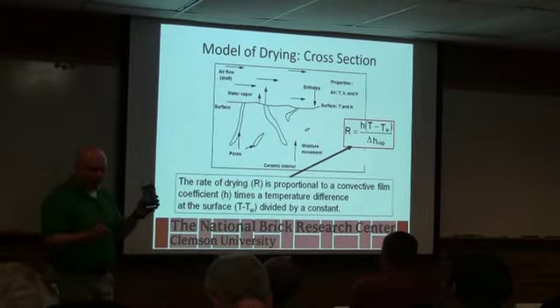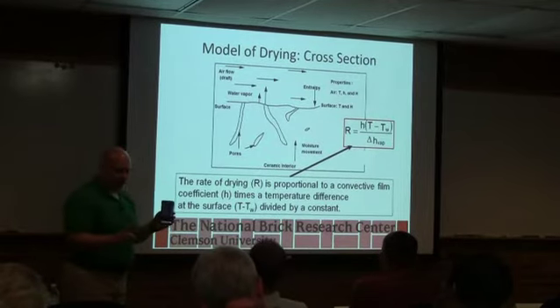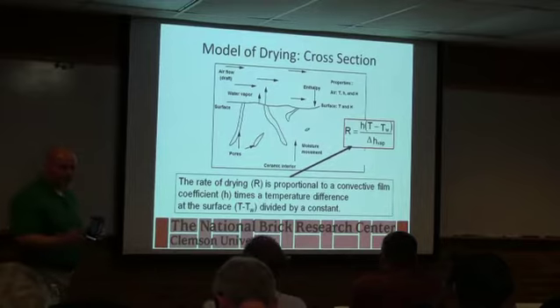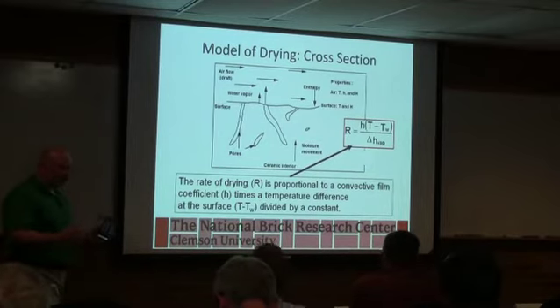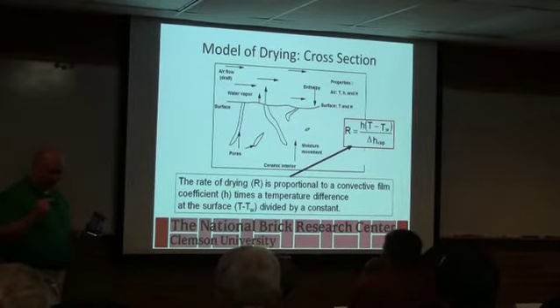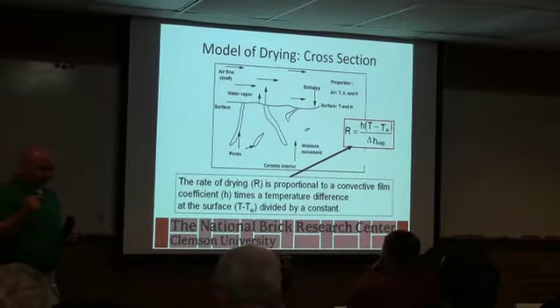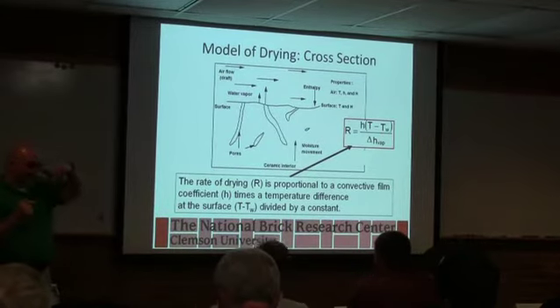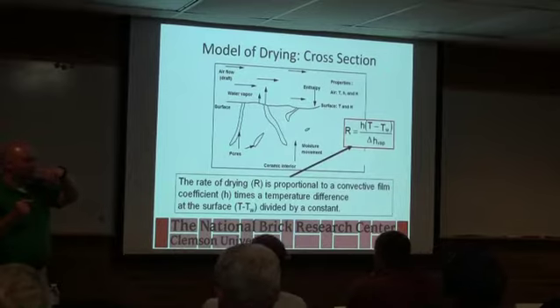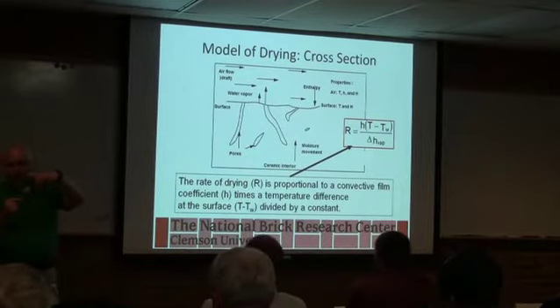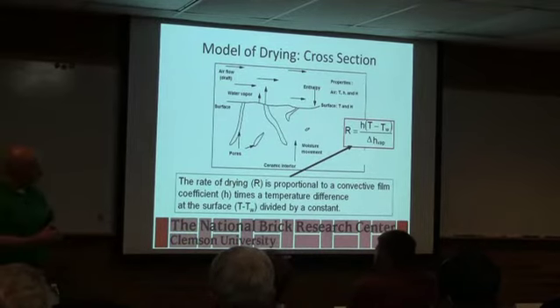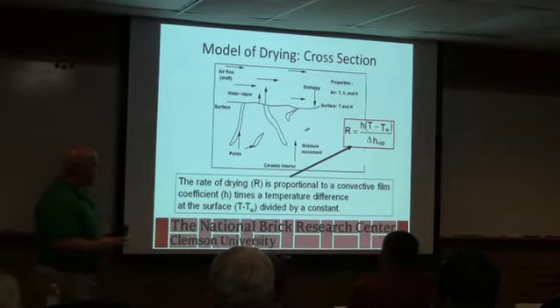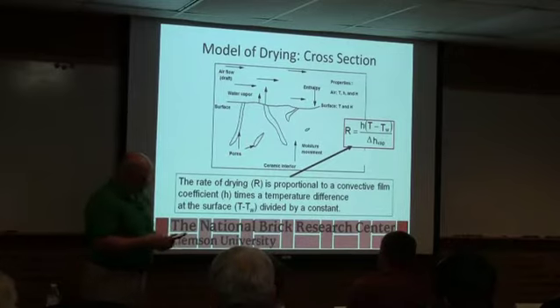Remember, relative humidity is relative to temperature. Okay, so if I'm looking at 50% relative humidity and it's 30 degrees outside, that's one moisture content. If I'm looking at 50% relative humidity and it's 80 degrees outside, that's another moisture content. Big difference in how much actual water's in the air, even though it says relative humidity. So typically when you're dealing with drying, we look at something called absolute humidity.